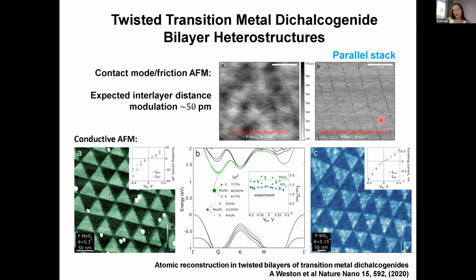And the reason for that is that although both of those triangular domains are 3R type stacking, they are effectively flipped upside down relative to each other. And that results in it being easier to tunnel into the one which is one way up as opposed to when you've turned it upside down. So in fact, that's a relatively large factor. As we can see here, we get an increase of about 1.5 times easier to tunnel into that region because of differences in the electronic structure within these two materials, two different stackings upside down.